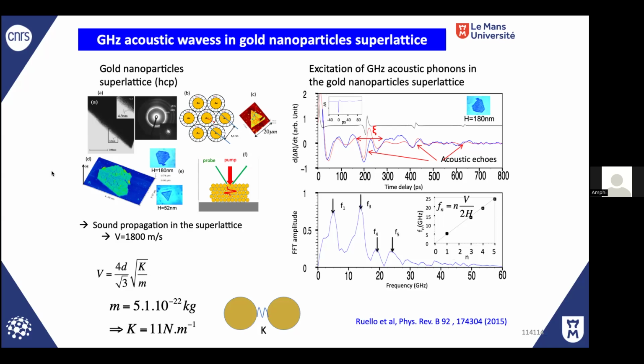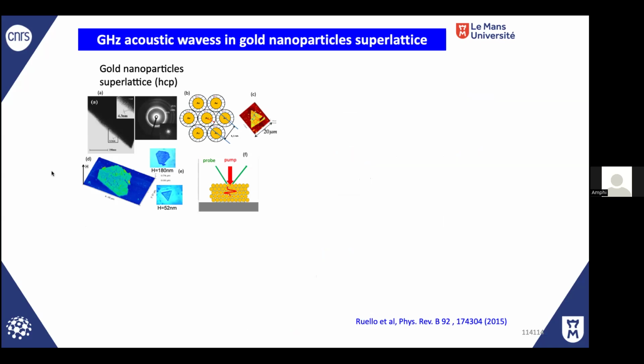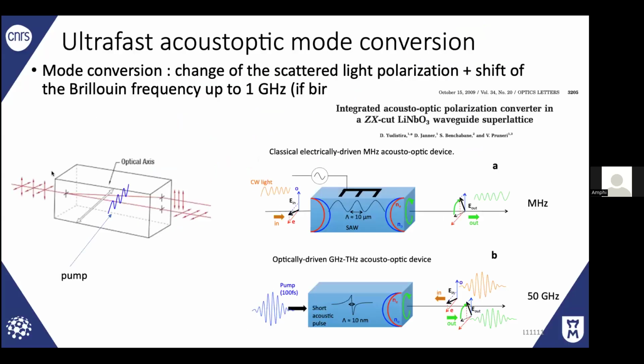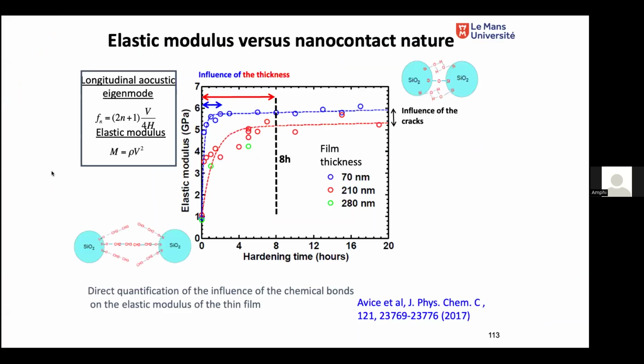We did it. I have no slide about that, but people did it with graphene layers, and they observed this oscillation. What I can show you as well is that you can modify the nature of the bonds between either the film, the 2D materials, or the nanoparticles, and you can measure it. It's, I would say, quite simple.